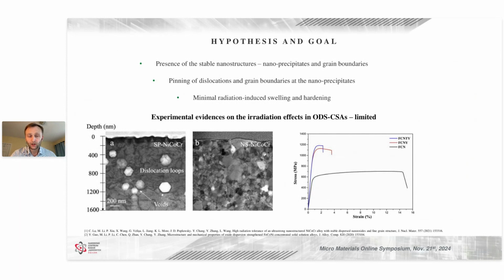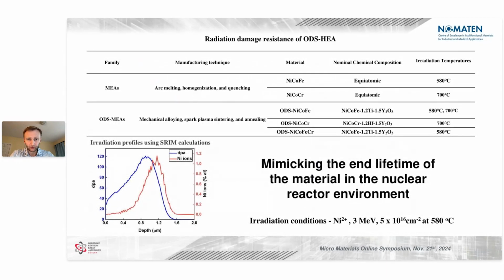by radiation. Therefore, we want to build a material which is resistant to swelling and hardening by introducing a lot of nanostructures. For this purpose, we manufactured single crystal alloys and alloys with the precipitates. We submitted them, in collaboration with our US partners, to irradiation at 580 and 700 degrees.